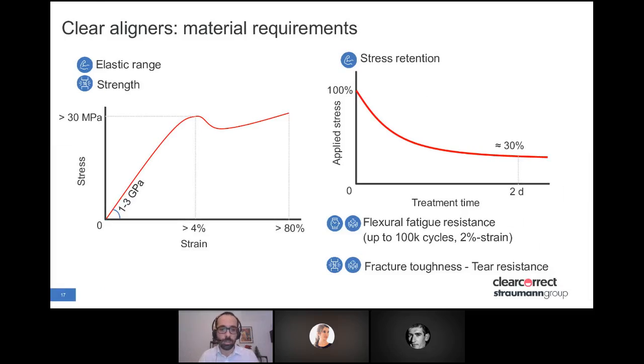These are translated into material requirements, as shown here. For example, quasi-static properties like tensile and bending. They should have a large enough elastic range, so a minimum yield strain of 4% and stress of 30 megapascal. They also have to have a higher strength. One property which is really crucial is the ability to retain stress, or stress retention. Polymers are viscoelastic materials. They tend to flow under a constant applied deformation. They tend to relax the stress, which is exactly what we don't want, because we want to apply a constant stress over time. So if you have a drop of 70% in 2 days, you have to start from a quite high initial stress in order to still have a certain amount of stress applied for the treatment.